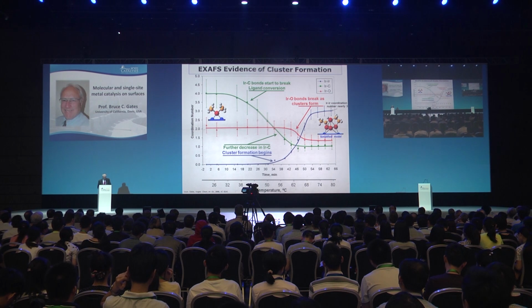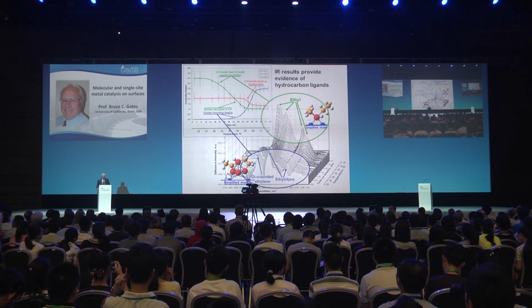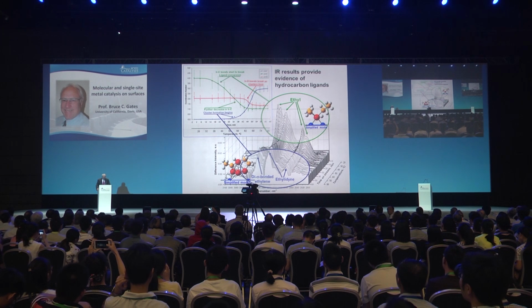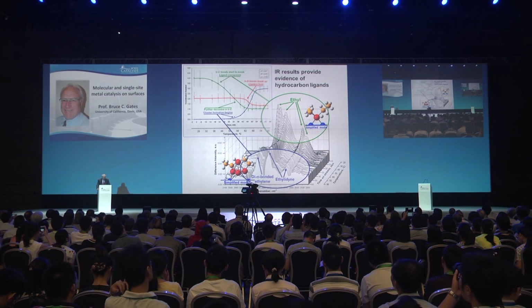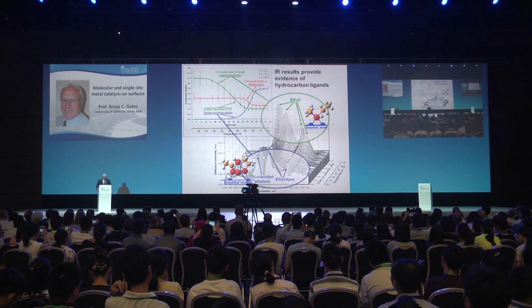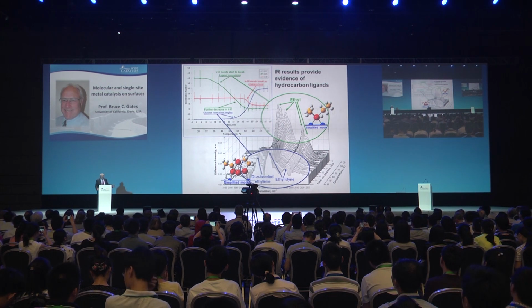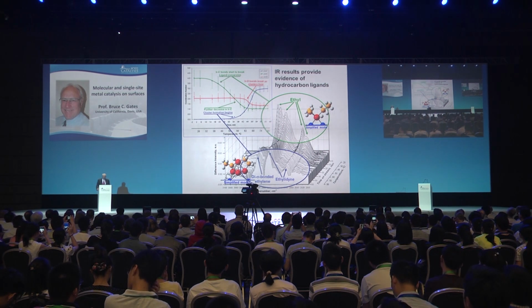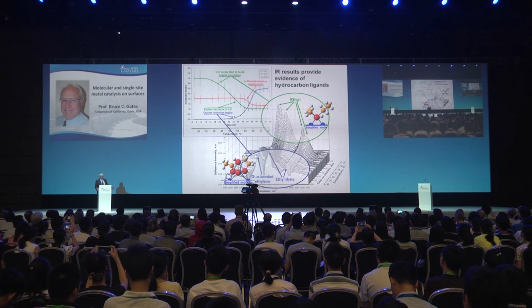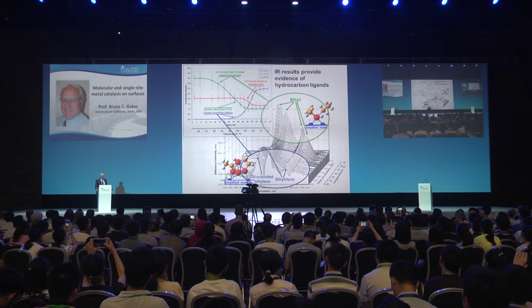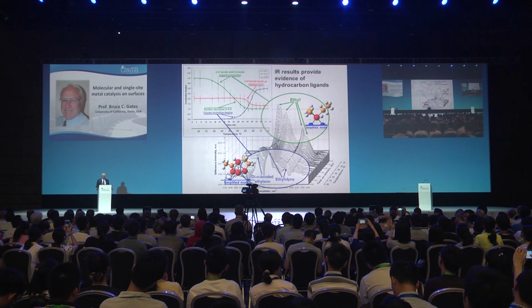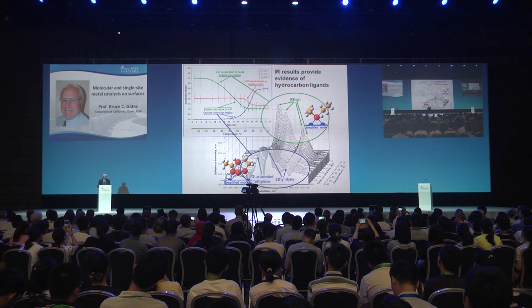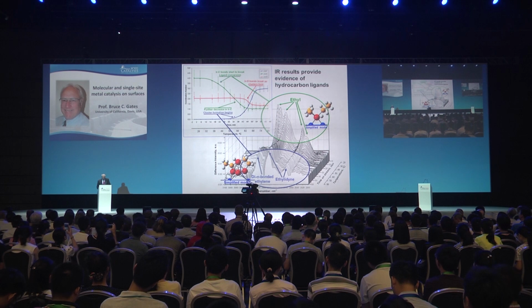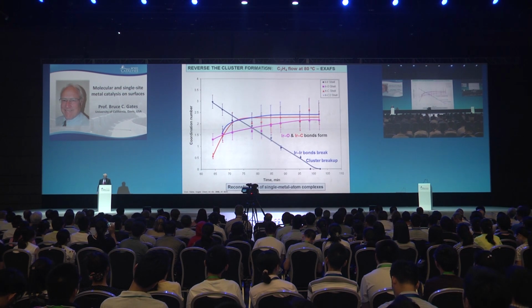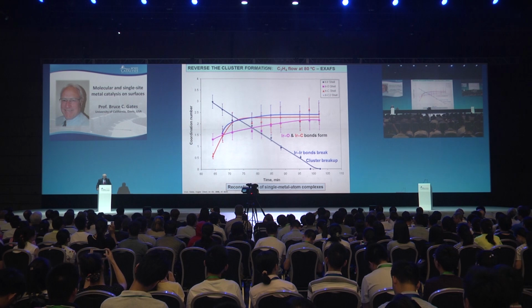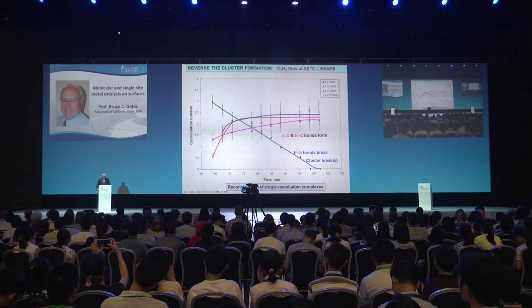We look at that in the infrared spectrum as these changes take place, and we see that not only are we removing carbon-containing species from the cluster, but we're making some that bridge between the atoms, which requires neighboring metal centers. So you see intermediates familiar from surface science work showing how hydrogenation occurs on metal surfaces. That whole process of cluster formation can be reversed, and it can be done in a cyclic way.